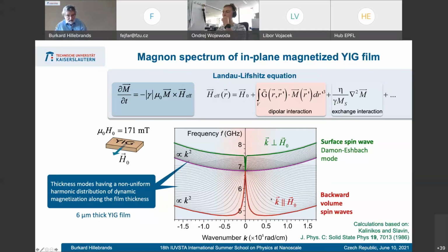And if you like to take another angle of view on this kind of data, you can consider this here as a long continuous range of frequencies, because the frequency spacing becomes very, very small here, where you can excite magnons in such a system. And you find something else which is also very exciting. You see there is a minimum here at a finite wave vector. And this leads us to the second part of my lecture a little bit later, where I will talk about Bose-Einstein condensation. So this all is there, and so let's move on.